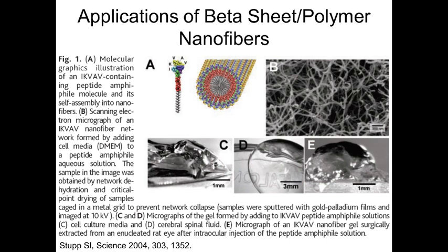What has been done here is a peptide amphiphile has been synthesized by using solid phase peptide synthesis. When you start watching the structure, you see that there's a long alkyl chain attached to one end of the peptides. Then there is a glycine alanine motif shown here in red. This glycine alanine motif is meant to form a beta sheet structure, so to make a strong assembly in aqueous solution.